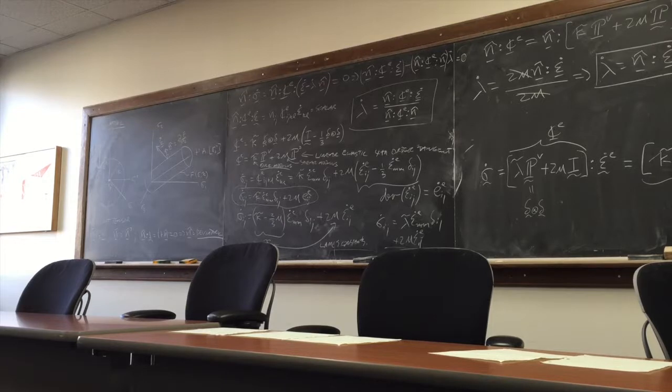When would you get lambda dot equals 0? There is one special case. What's the condition? So the trivial one is epsilon dot equals 0. Okay, fine. The orthogonal. Right. When epsilon dot is tangent to the cylinder, then you will get a perfectly orthogonal strain increment. And let's see if we can figure that out.